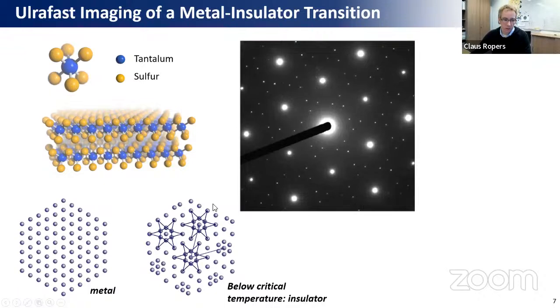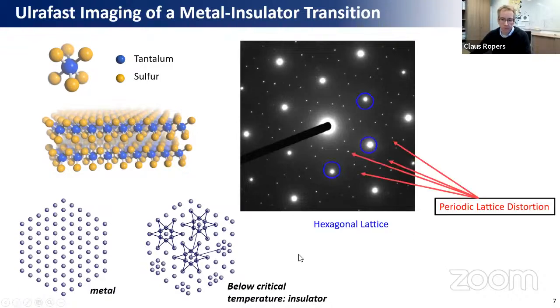Yeah? So the actual size of the unit cell, of course, in this superstructure crystal is larger, which means this leads to smaller diffraction angles, essentially. And because it's only a subtle change in the lattice constant, so exaggerated here, but in reality only a few percent of the bond spacing is changed, these are about 2 orders of magnitude weaker than the main diffraction peaks. Okay, so yes, hexagonal lattice, periodic lattice distortion.